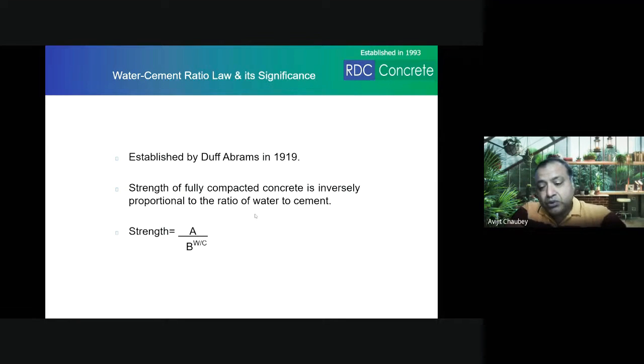So the second most significant factor on which the strength depends is the additive materials that you add into it. It could be fly ash. So if you are replacing more amount of fly ash, the strength will be lesser for the same water cement ratio. But economically, for getting the same strength with fly ash and OPC, you will get a better performance with fly ash, because fly ash is much cheaper.